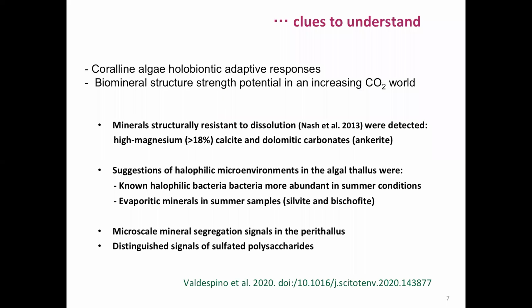And in summary, we think this multi-scale approach has been useful to provide some clues to understand 2 different aspects. One is the seasonal microbiota plasticity, potentially related to adaptive responses of their holobionts, particularly to thermal and nutrient availability pressures. The second is a description of a strong microstructure, because we detected minerals known to be structurally resistant to dissolution in decreasing pH, particularly high magnesium calcite. The content of the magnesium calcite was higher than 18% in our samples. And we also found dolomitic carbonates such as ankerites.